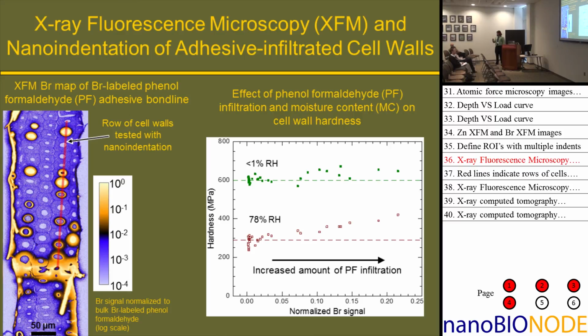So we calculate both modulus and hardness, but the hardness, for reasons in the nanomechanics of the cell wall, is more related to the moisture-induced softening of the matrix of the secondary cell wall. So I'm just going to show the hardness results. And what you can see here is that under dry conditions, there's not very much effect of the amount of adhesive infiltration, but under wet conditions, you can see that this adhesive had quite a large effect on the amount of moisture-induced softening that's happening inside the wood cell wall.